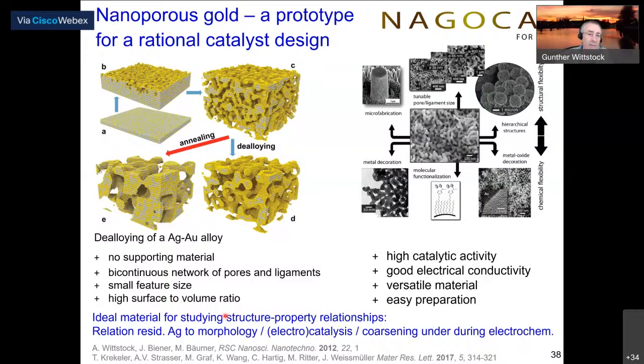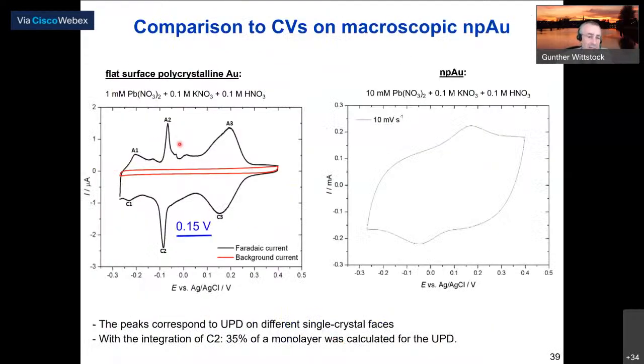And that is done not only in my group, but also in a research group funded by DFG. I'm the spokesperson of that, where we also investigate similarities and differences between gas phase catalysis, liquid phase catalysis, and electrocatalysis at those materials. So when we started, that was our result. We had a flat gold electrode. We tried to do metal underpotential deposition, and we also tried to do that at the nanoporous gold. And after half a year of work, this is what we achieved, and it was really disappointing.